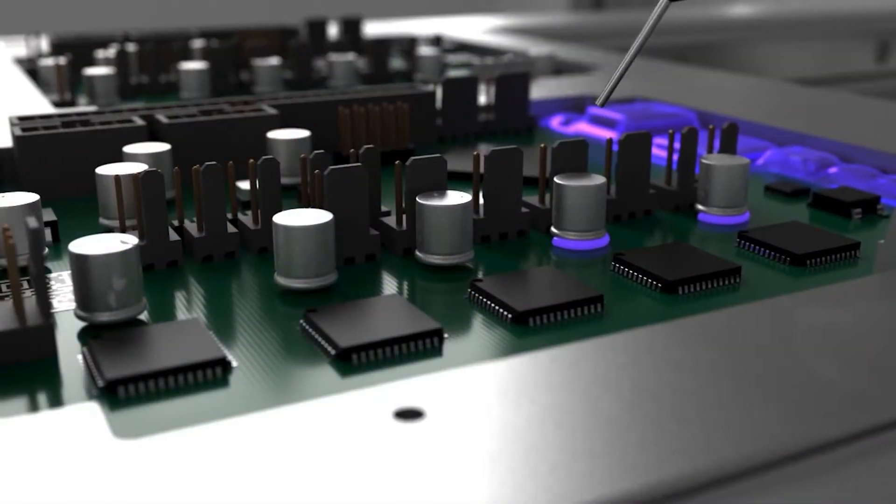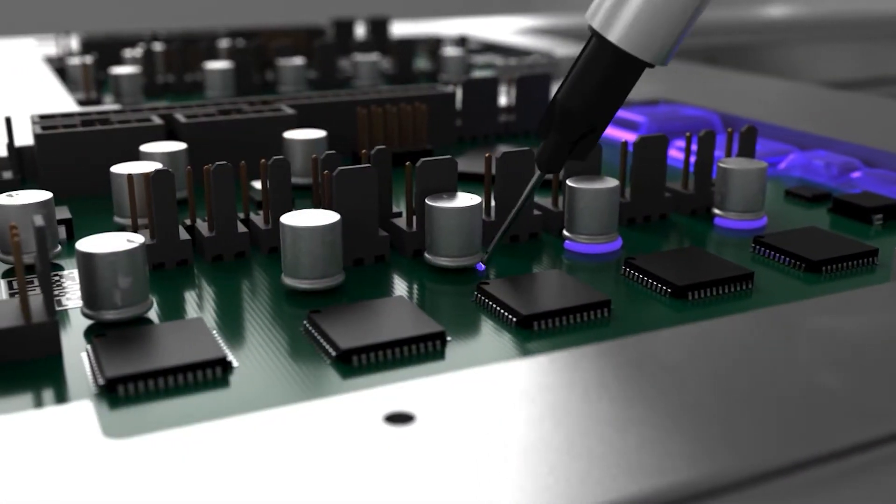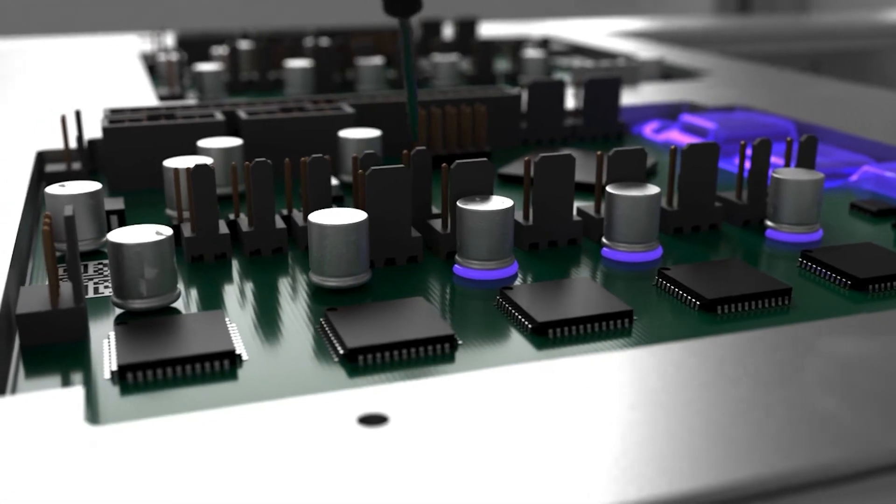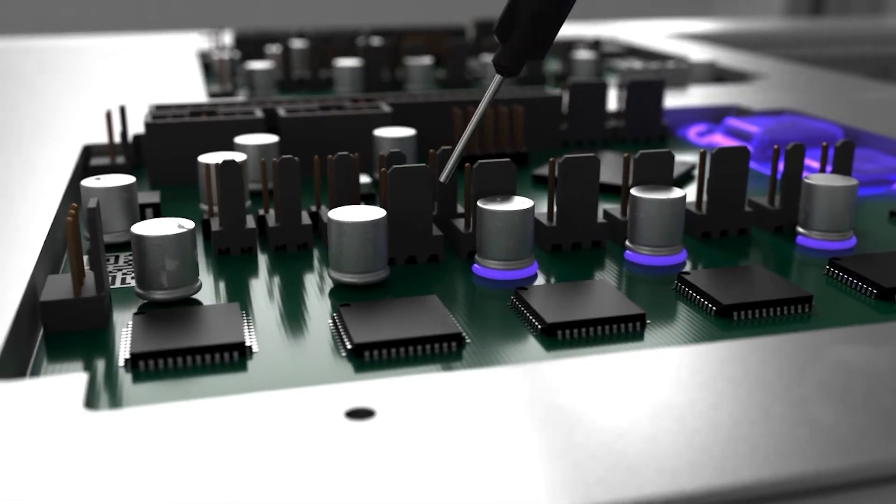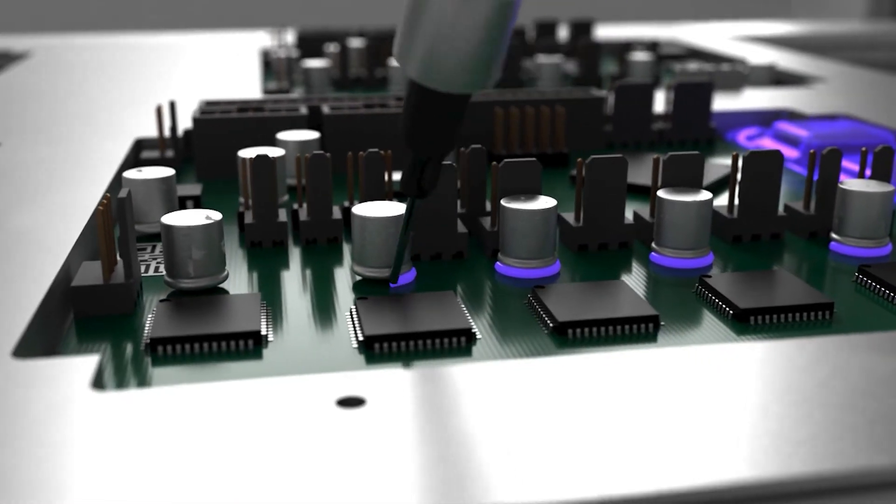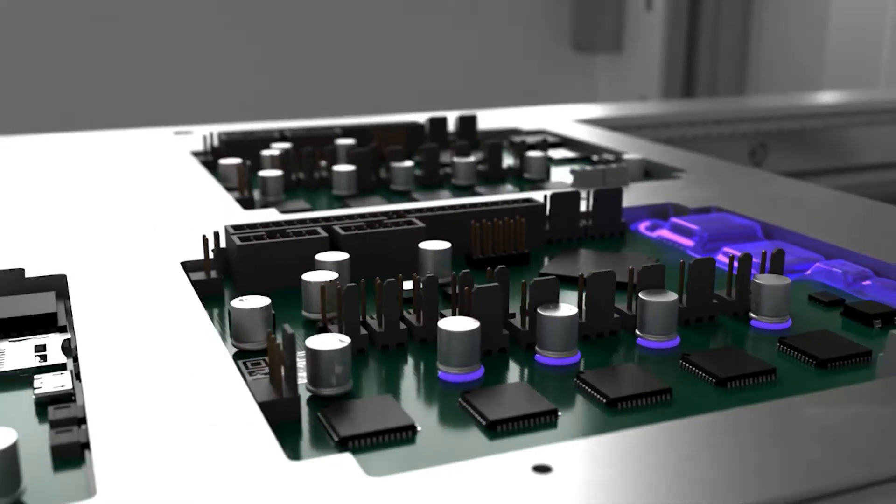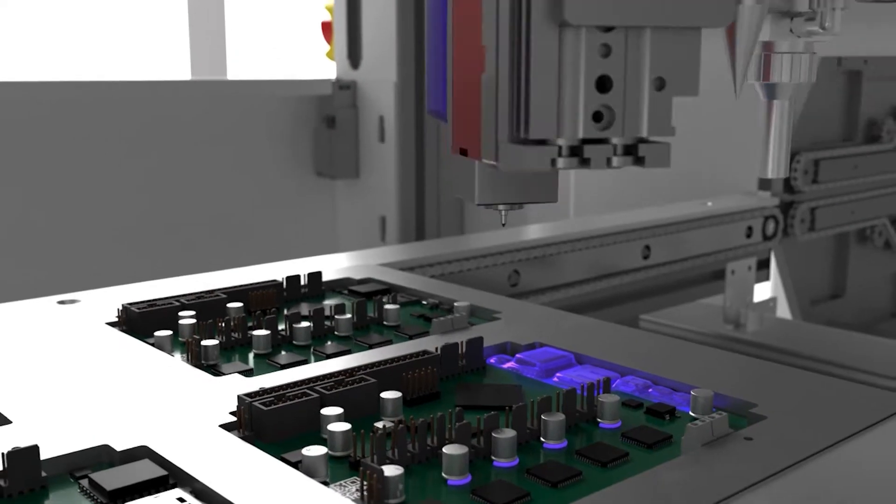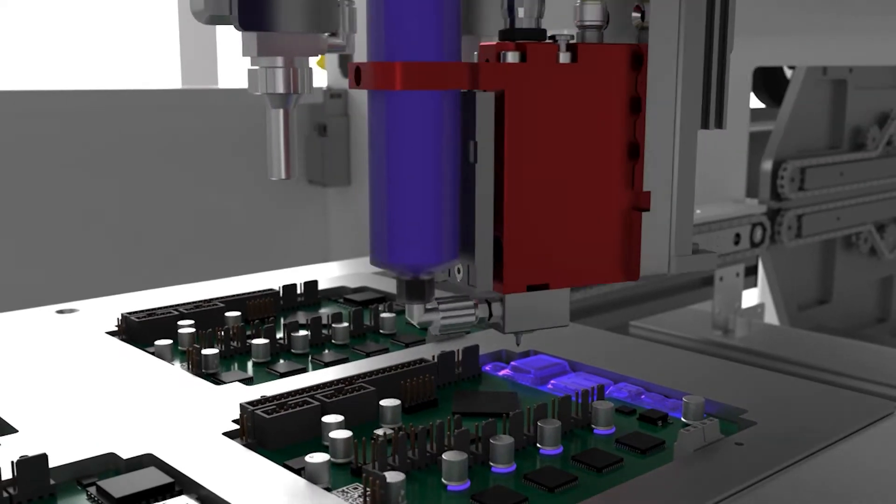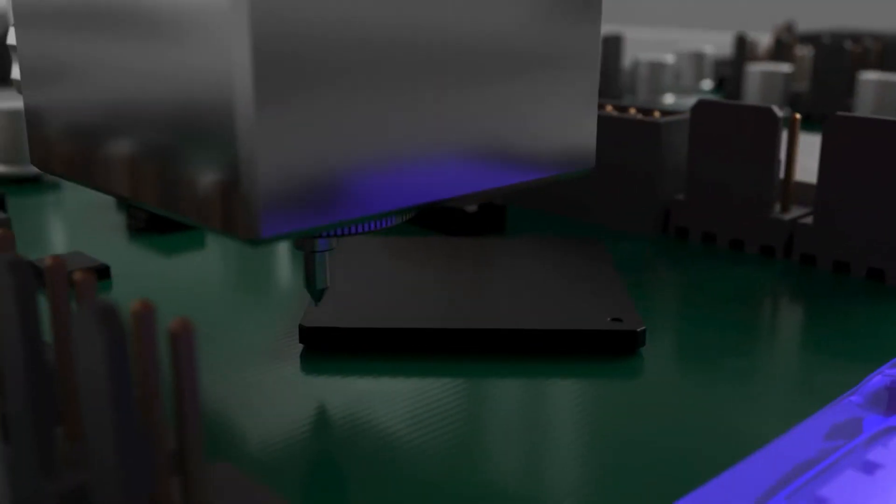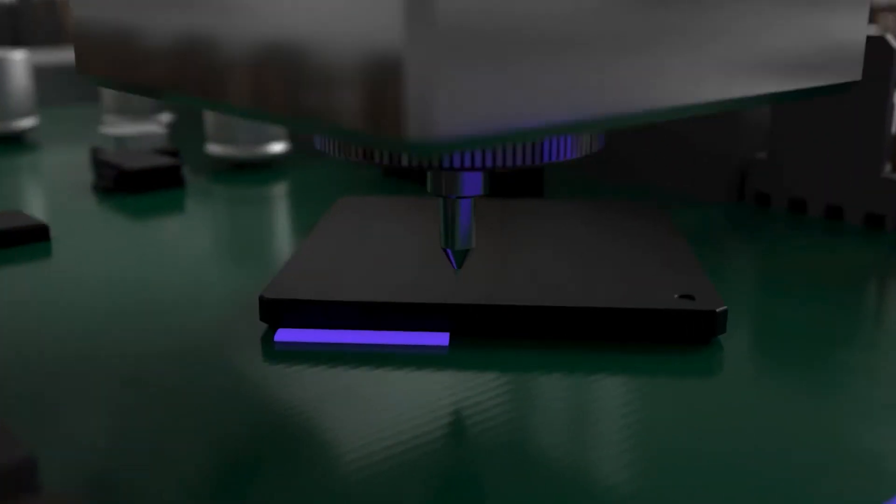Employing an underfill type process on trouble components can allow air to escape from underneath the component prior to applying the top coating layer. To perform this step, apply coating to at least two joining edges of the component with a detailing valve.